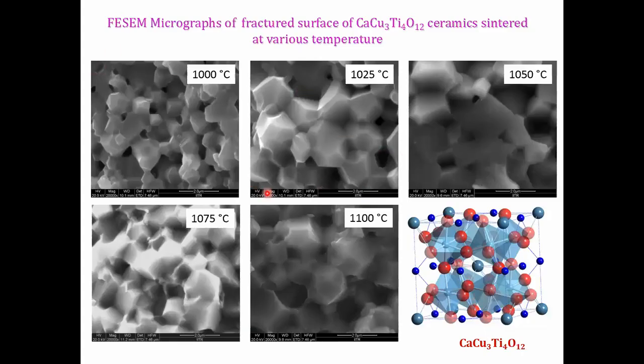This is the FESEM photomicrograph of the fractured surface of calcium copper titanate. You can see how grain size is changing at 1000 degrees, 1025, 1050, 1075, and 1100 — it is increasing size up to 1100. We checked above that too, but it melted at that amount, I will show you one place. Since it was melting, we didn't go higher. Then we heated the material at 1100 itself for 3, 4, 5, and 8 hours, I think.